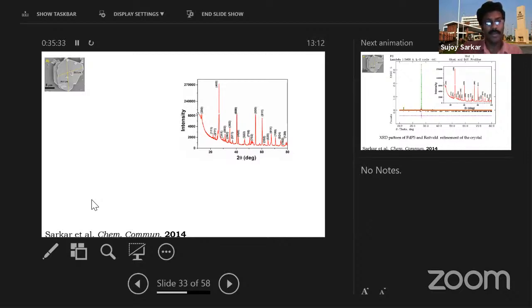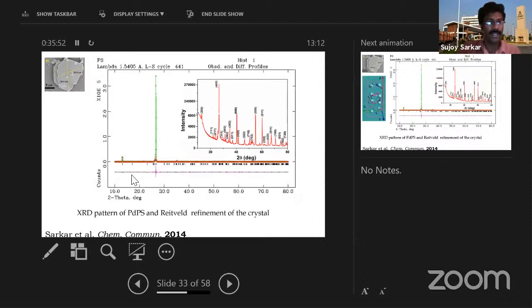With this different method, could I get another phase or another product, and can I find that out from my XRD? I see that it matches, but there are some small peaks that do not match the reflections available in the literature or from the single crystal data. So for that, we did another data collection. That is our data analysis, we can say.